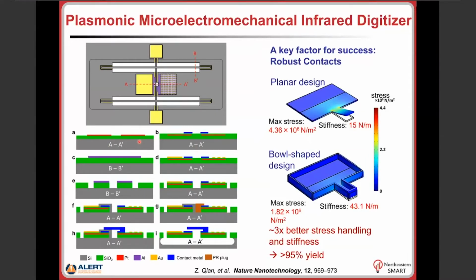It's really based on silicon oxide, aluminum, and we do use gold for the plasmonic absorbers, but other materials could also be used for integration with, for example, CMOS or electronics. The only thing that I want to highlight, one of the design features that I believe were very successful, and really were key for the demonstration of the functionality of the device, has to do with the design of the contact tip.